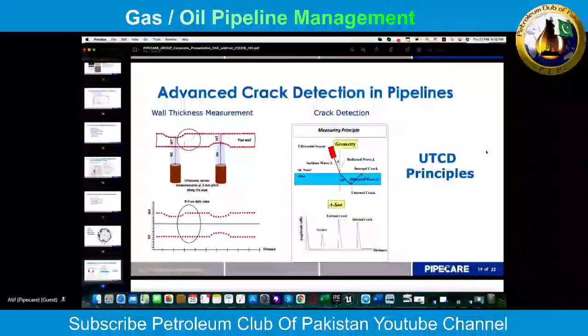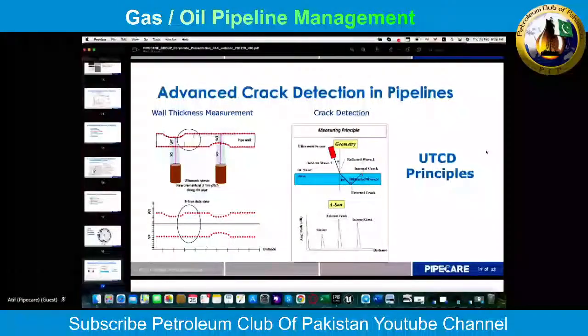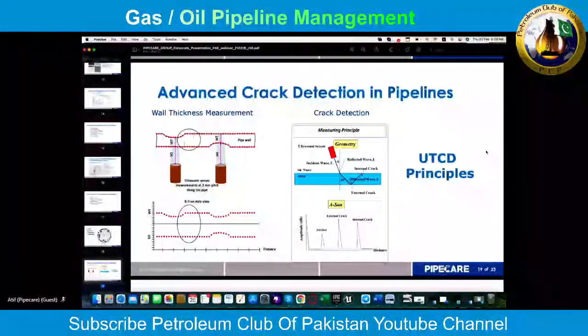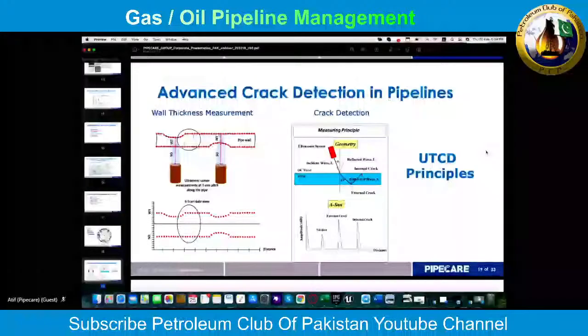Now we need to understand what is special about the crack detection tool. Why can't we use our standard ultrasonic wall thickness measurement tool? The explanation is that the UTWM tool sends the ultrasound perpendicular to the pipe wall. And as the cracks are also perpendicular to the pipe wall, the ultrasound will miss these cracks. So the data analyst will see nothing in the data.